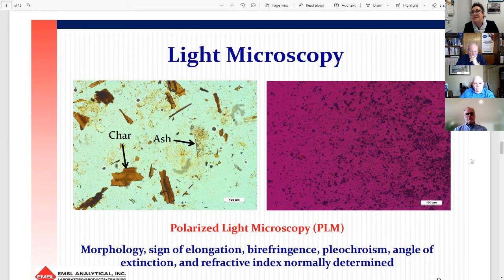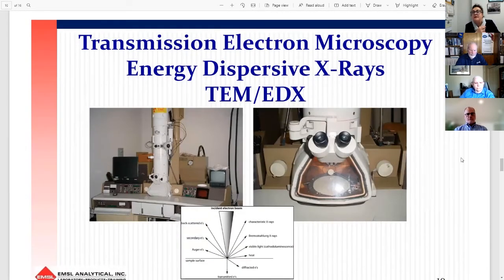But we can't tell you for sure by this method alone that there is only soot in the sample, because we do not see the aciniform morphology, we don't see the size, we don't see how the particles agglomerate. We can't really tell you for sure that this is soot or not. So this method, most likely used just like this for soot, will overestimate. I will give you that this will be maybe 80% soot, and it may be less, but by this method alone, expect 80%.